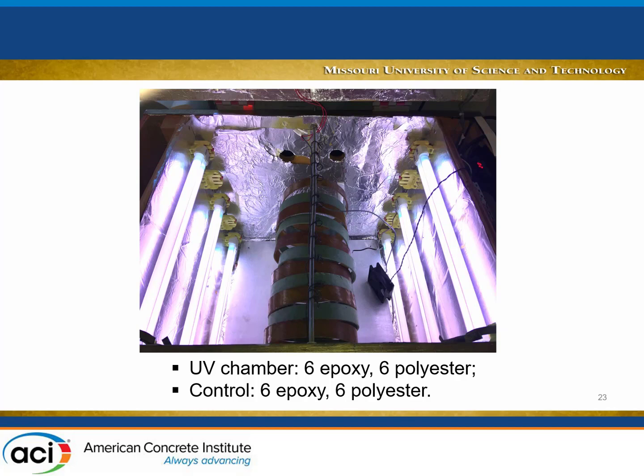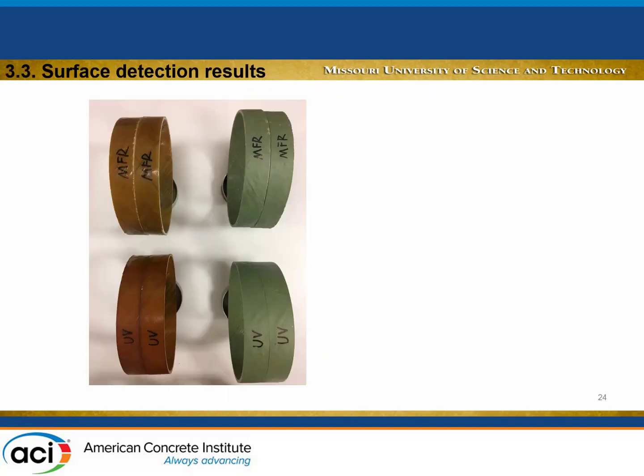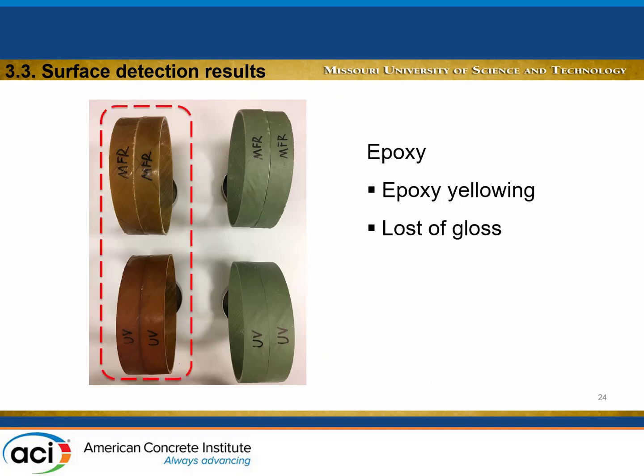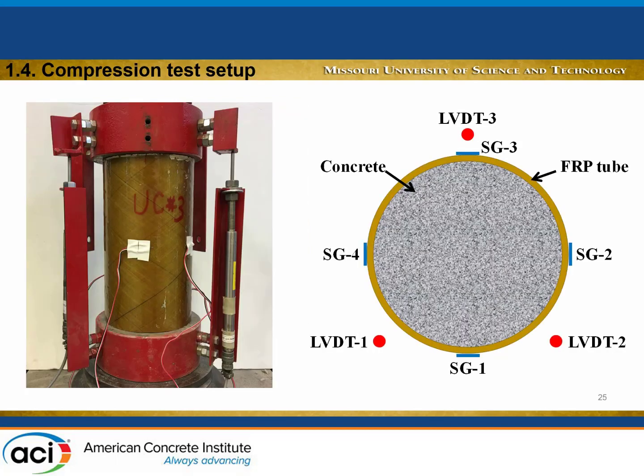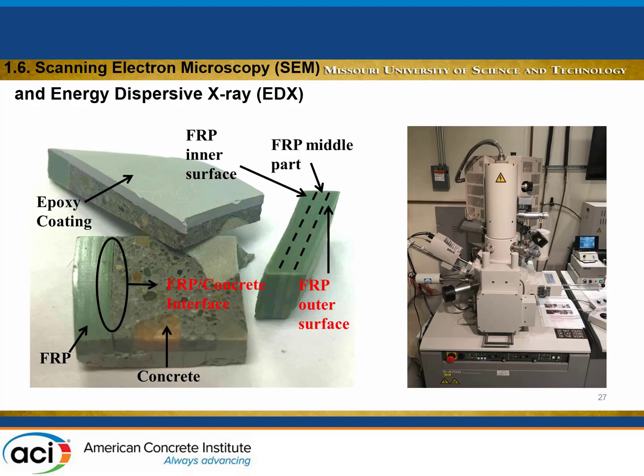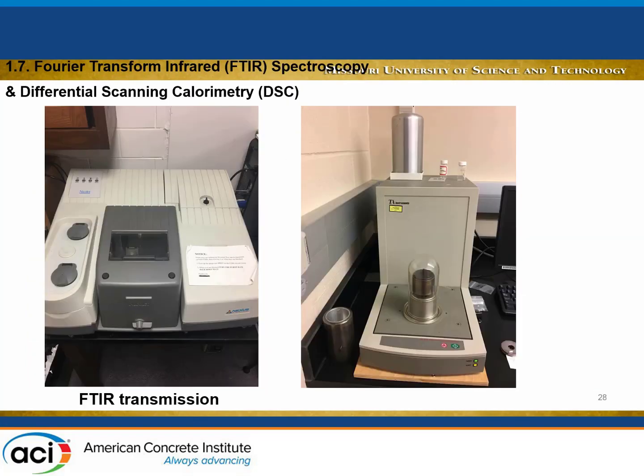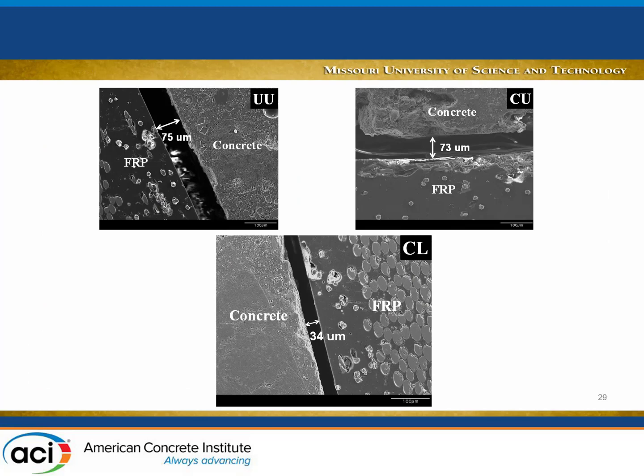On the other group, what we did is we sliced the FRP pipes, and we placed them in a chamber where we subject them to UV rays. So these are the rings, and we did this for epoxy specimens and also for polyesters. Once we take a cylinder out of each of those groups, we apply compression, and since our interest was in seismic, we apply a cyclic axial load. We also did some microstructure analysis, FTIR, and this is one of the interesting things.